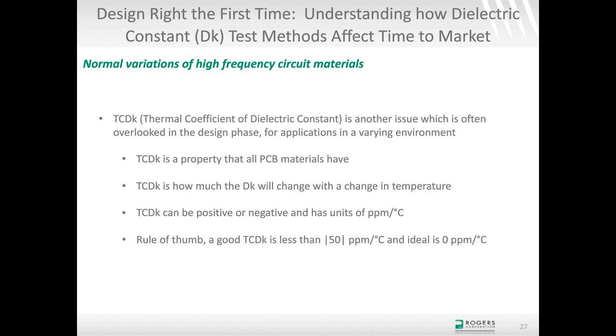TCDK, thermal coefficient of dielectric constant, also sometimes called temperature coefficient of dielectric constant. Basically, that is how much the dielectric constant will change with a change in temperature. And all materials have TCDK, some materials much worse than others. We formulate our materials to have very low TCDK, and the unit of measure is parts per million per degree C, and that's basically saying the dielectric constant is going to change in parts per million for every change of temperature in degree C. And the general rule of thumb there is a material to be considered good for TCDK would have 50 parts per million per degree C or less. Ideal would be zero, or in other words, no change in dielectric constant with a change in temperature.